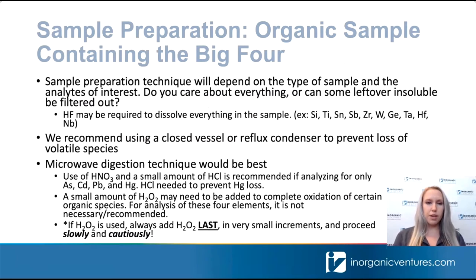That brings us to sample preparation. So in this section, I'm going to focus on organic sample types containing these four main elements. Of course, your sample preparation technique is going to depend on the type of sample that you're analyzing, as well as what you need to analyze. So for some sample types, hydrofluoric acid may be required to completely dissolve everything in the sample. But hydrofluoric acid can add some additional concerns for the analysis, for stability of your working solutions. Will something drop out as an insoluble fluoride if you add HF? And then also those concerns for glass instrument components and safety issues with using HF.